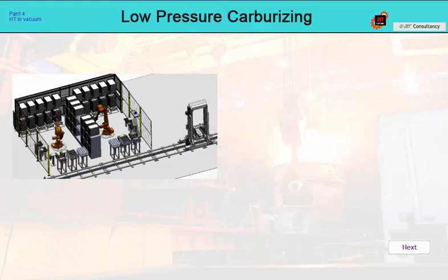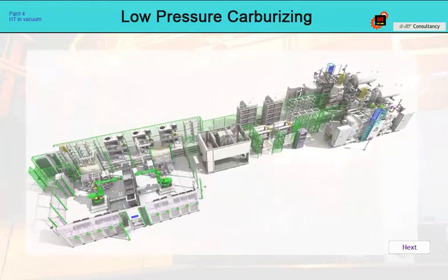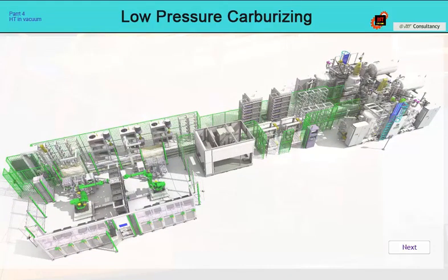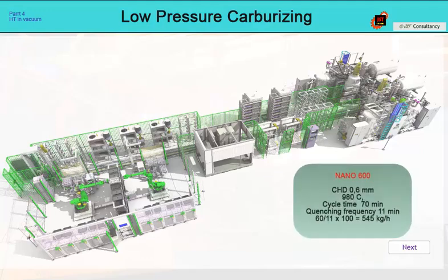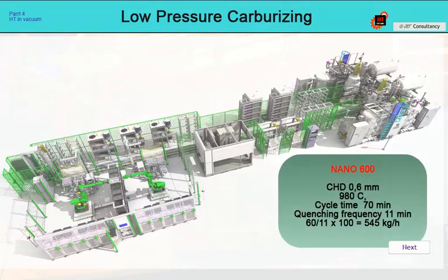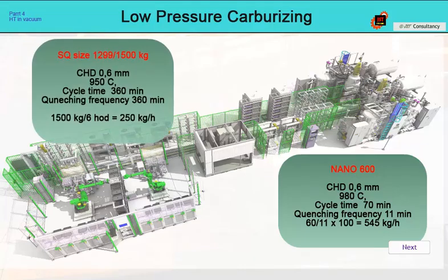Everything that was previously stated applies to carburizing in this system, but because we have 6 carburizing chambers, for example, for CHD 0.6 millimeters, the quenching frequency will be up to 11 minutes. This means that in this device, we can carburize up to 545 kilograms of charge, including grates in 1 hour. And this is more than in a conventional multi-purpose furnace with the load of up to 1,500 kilograms.